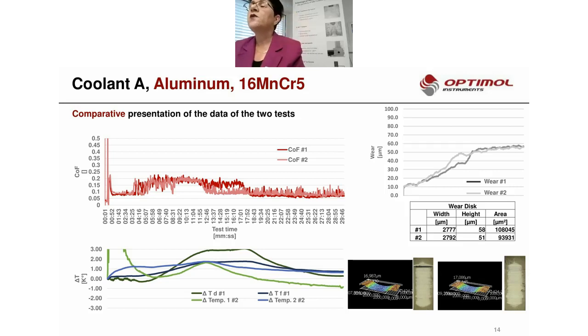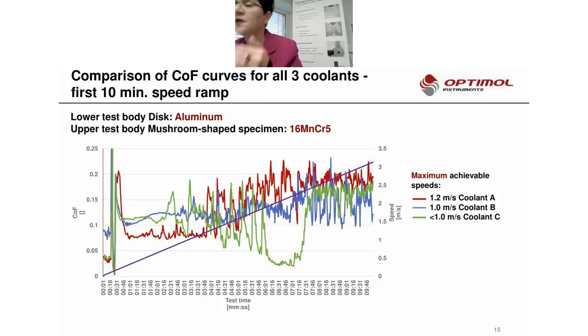Okay, we have seen that repeatability is absolutely given also with this combination, and the wear values are straightforward, a little bit higher than in the case of steel. But we could not make that kind of nice ranking between coolants A, B, and C. We made a ramp from 0 to 3.15 meters per second, the velocity which we also used for the steel. And in the case of aluminum, we were too fast. We have to repeat all the tests under 1 meter per second.